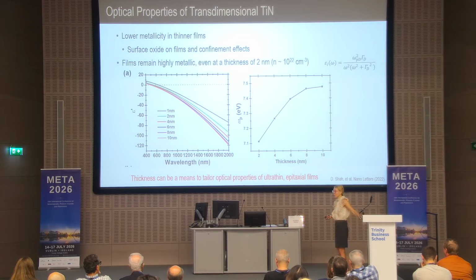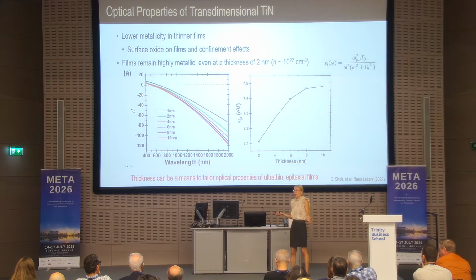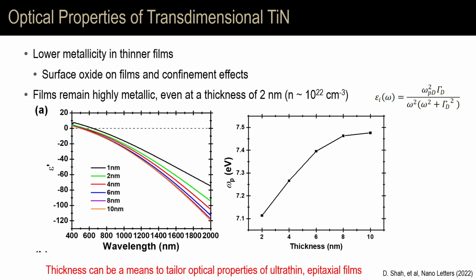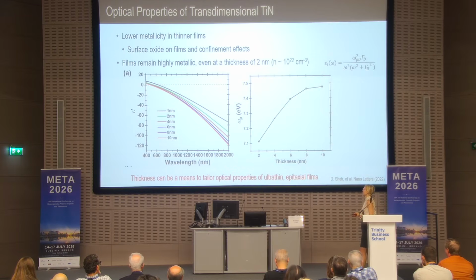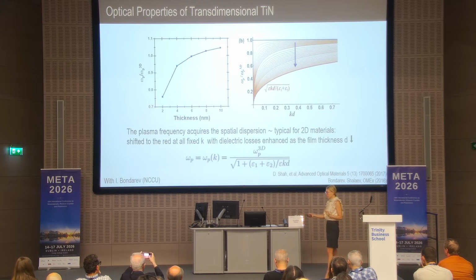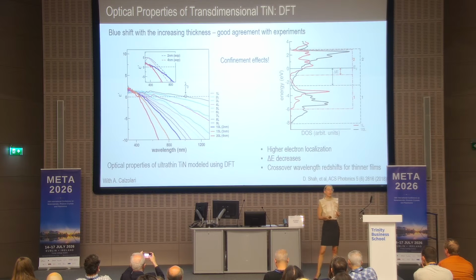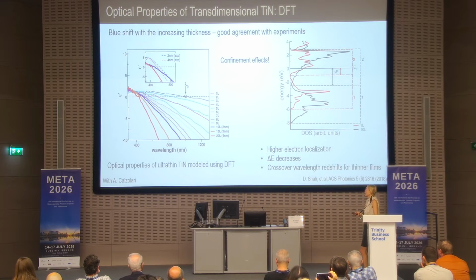The first demonstrations that we did is obviously just to see how the optical properties are changing. What we showed is that indeed in the ultra-thin titanium nitride films, you have a lowering metallicity with a reduced thickness. But in this specific case, films do remain metallic until they're very thin. We worked with theory people, and this is a group of Arrigo Calzolari who actually ran DFT calculations, showing the same trend as we saw in experiments, that our plasma frequency is changing with thickness,